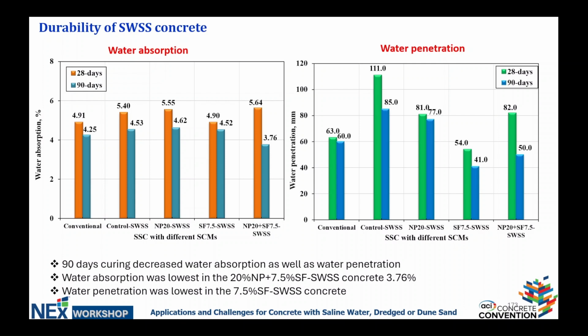The durability, depending on how you measure it, there are many ways to do it, and the water absorption could be one of them. And as you can see here, there is not much difference between the mixtures. But if you look at the water penetration, the mixture that only has seawater and sea sand obviously is the one that is most affected by the water penetration.